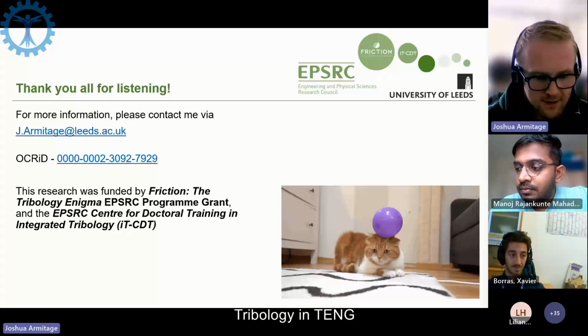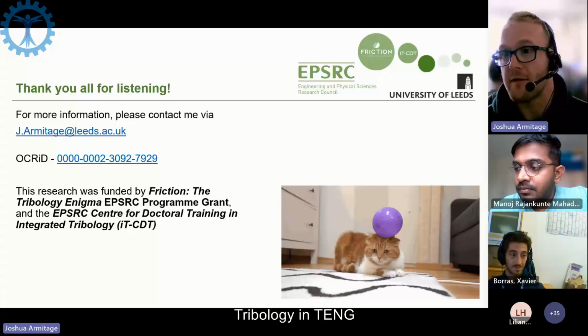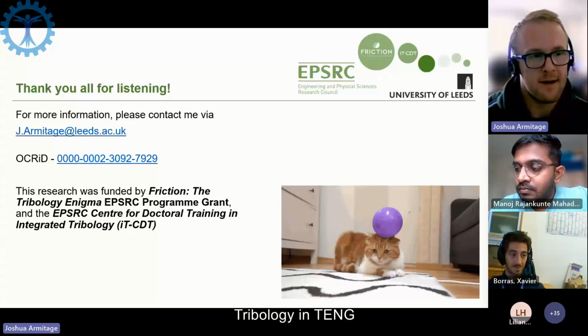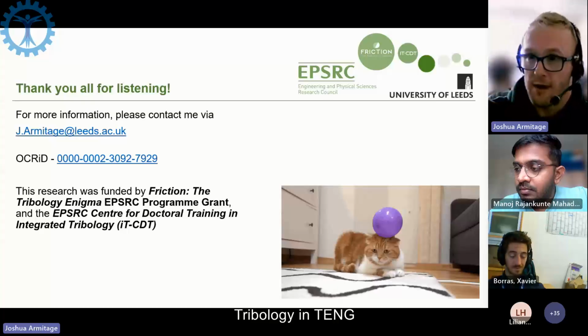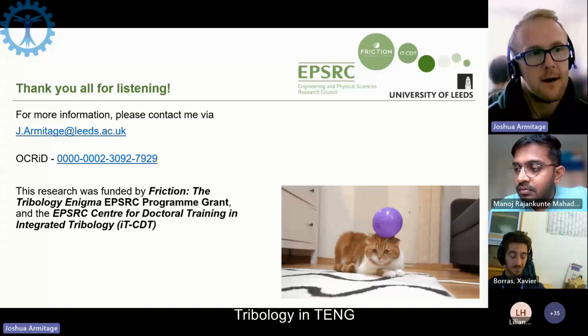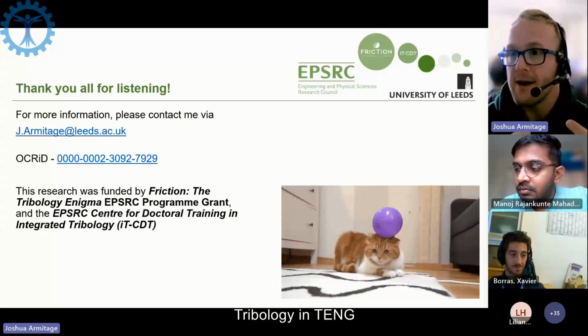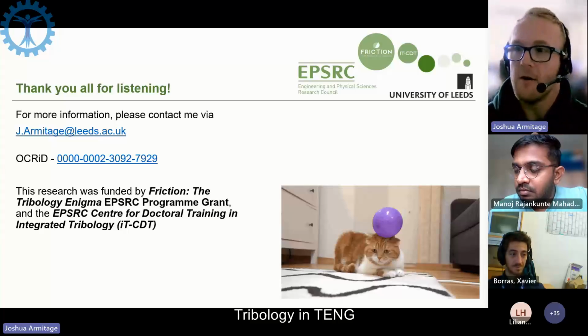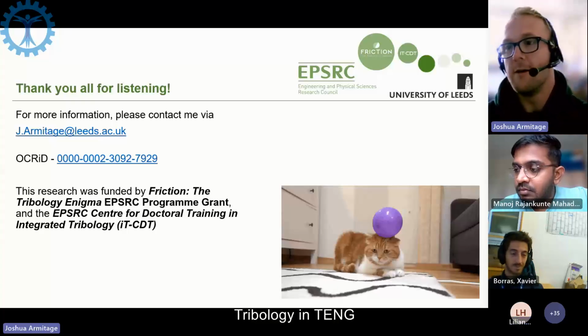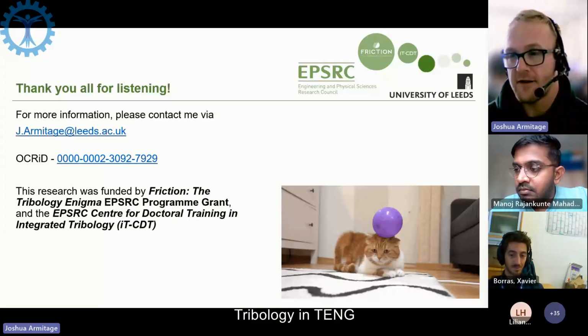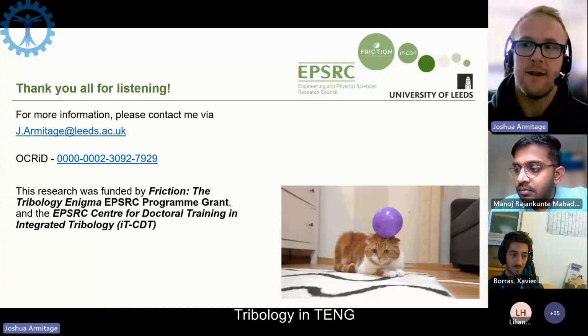Yeah, exactly. This is something I'm hoping to move my research forward to investigate on a nanoscale with AFM. I think that adhesion not only plays a part mechanically in terms of the stretching of bonds upon release, but I believe it would enhance charge transfer because you're not only modifying the electronic structure by compressing it in one way, but bonds that may be stretched one way may be compressed the other way, and vice versa. You're diversifying the electron states within that surface.